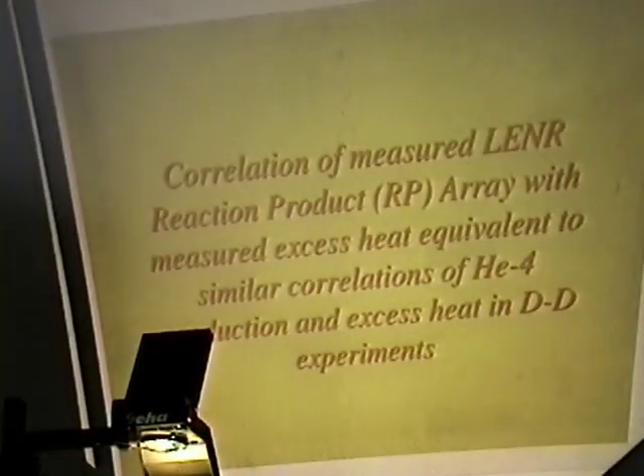I'd also call attention to the other poster that day, 066, which relates to this, and which I'm giving, on the fact that if you take this array of products that's observed, multiply by binding energies, and subtract the initial fuel binding energies, you get a relation which correlates reasonably well with the heat produced in those runs. In other words, this array of products and its measurement is, to this field of LENRs, the equivalent of the measurement of helium-4 in the DD reaction, as has been discussed in the previous talks.